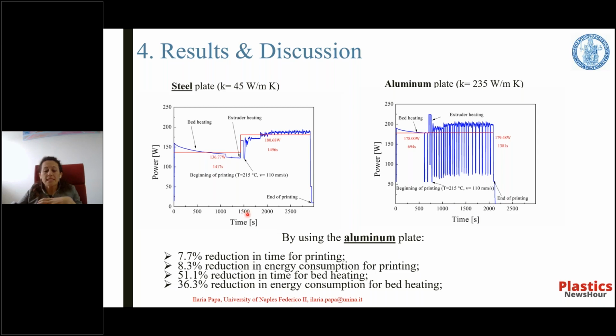Here we can see the power trend of the same configuration during the FDM process by using the steel plate and also the aluminum plate. And we can see immediately that the bed heating lasts less using the aluminum plate than the steel plate. This result is due to the fact that the thermal conductivity of the aluminum is higher than that of the steel plate. Moreover, by observing the printing phase of the diagram, we can see that the average power during the printing with the aluminum plate is lower than that using the steel plate.